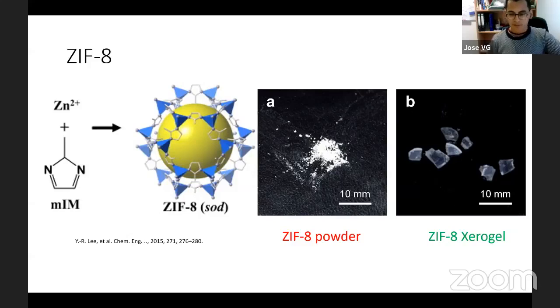So what happens with the ZIF-8, with practically every MOF which is obtained in powder form, is that the MOF is compressed to form a pellet. However, this compression can produce a collapse of the pore, and then the quality of the final material is less than the crystalline or original form. When you create a xerogel, you don't need any compression. You already have micro pieces which are quite manageable in the industry. So you don't need further processing. So you can directly use and conserve the pores or the properties. Sometimes the properties are even better in the xerogel than in the powder.